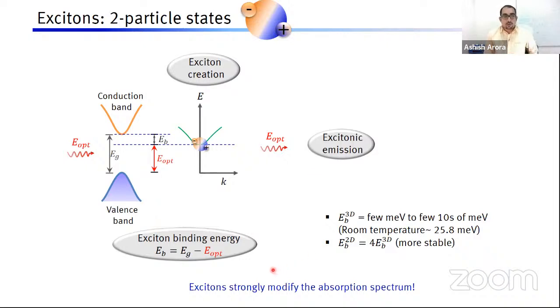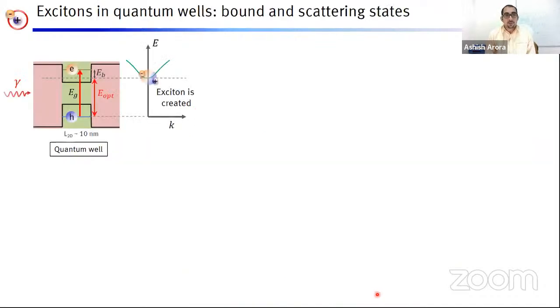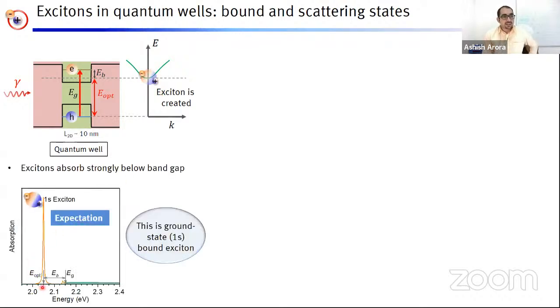Now, we will be talking about optics, and excitons strongly modify the absorption spectrum. Let's look into some basics of this. Let's suppose I shine a photon on a quantum well where a semiconductor such as gallium arsenide is sandwiched between two barrier layers of aluminum gallium arsenide, and then the electron and hole levels are quantized, and we can have optical transitions. Now, an exciton is created. This will be a two-dimensional exciton. What we expect is that this exciton will appear as a strong resonance just below the band gap by an amount equal to the binding energy in the absorption spectrum.